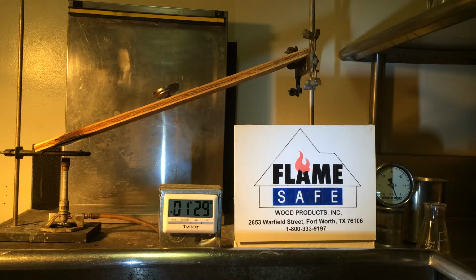The ASTM D2898, which refers to the accelerated weathering of fire-retardant treated wood for fire testing, was done under Method A. The slope of the panel was set at 4 inches in 12 inches for the rain test procedure. And it was subjected to 96 hours of water exposure and 72 hours of drying for a period of 12 one-week cycles.